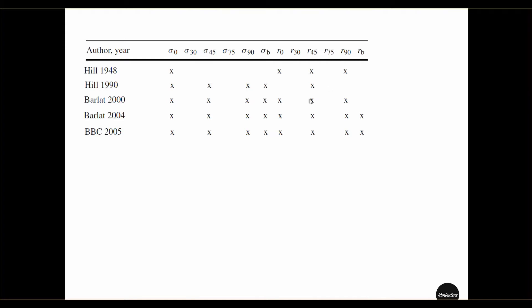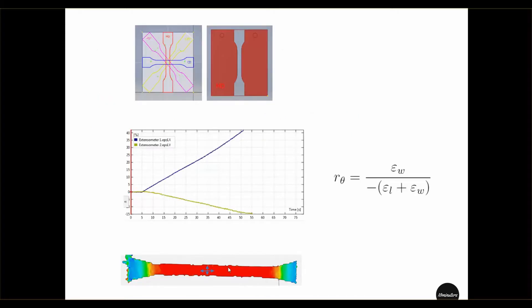For defining the Lankford coefficient you need measurements from digital image correlation or DIC. One way is to take any orientation — for example MD or zero degree — and do a tensile test together with DIC measurement. A tip is you can do this DIC measurement freely and easily during your tensile test by placing your mobile camera and recording the video. Before that you have to put a speckle pattern on the specimen by spraying paint from a regular paint can. Once you have that video, you can analyze it in the free software CorRelate, where you can place virtual extensometers in the width and length directions.